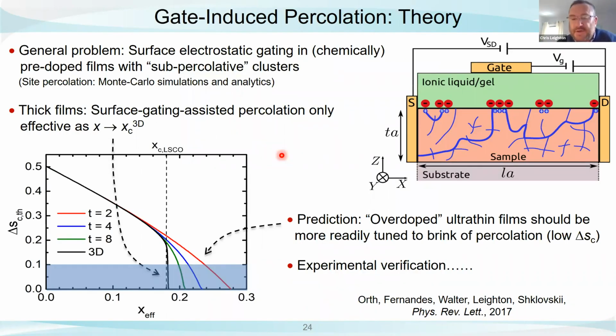I think I'll gloss over here, unfortunately, the theory of this. This was published in PRL in 2017. Very nice work by Boris Shklovskii and Rafael Fernandes, our collaborators. What they basically did is percolation modeling. And they showed us that our original idea wouldn't really work. You have to be incredibly close to the percolation threshold to be able to gate across it. But what they also showed us is if you just keep the doping high and you go down in thickness to the two-dimensional limit, you go under the percolation threshold that way, essentially going into the dead layer, then it should be much easier to gate it back into a ferromagnetic state.